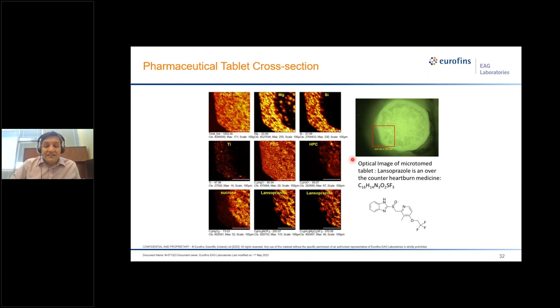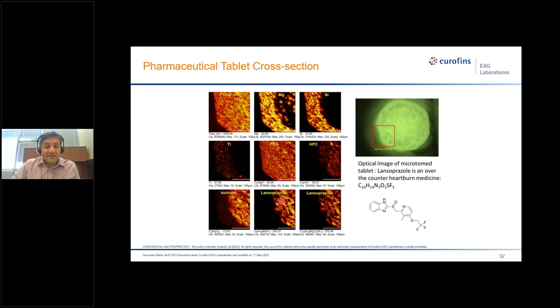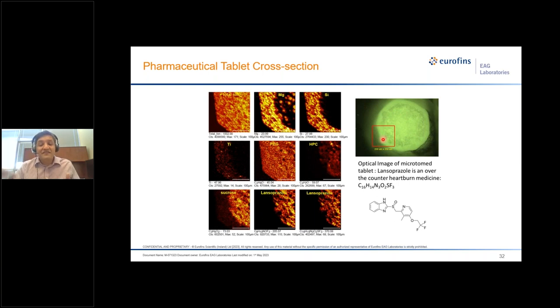For imaging capability, here we have a pharmaceutical tablet cross-section, analyzing a 250 × 250 micron area. The API is Lansoprazole, an over-the-counter heartburn medication. It has multiple components, and it's important to know where exactly each component is present. The two characteristic ions for Lansoprazole show it is present in the interior of the analyzed area, not on the exterior. Magnesium and silicon are present mostly on the outside, with some magnesium inside as well. PEG is present throughout the entire analyzed area, while cellulose and sucrose are more toward the inside. This gives us the distribution of different compounds within the analyzed area.